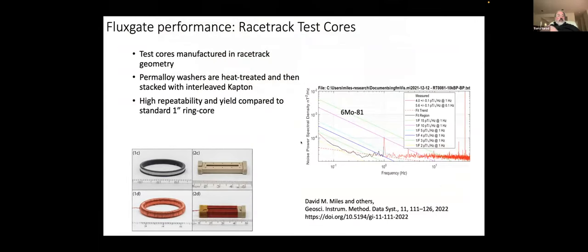Okay, on to looking at what the actual noise performance of some of these things are. We started by sticking with the 6% molybdenum legacy material and making magnetometers based upon 100 micron foils. Here you can see a ring with these 100 micron foils. And David chose to develop a system of making racetrack sensors rather than ring sensors, which have ultimately proven to be quite a lot better. Here inside this plastic case are layers of foil washers cut into a racetrack shape, with then the windings put on top of it.